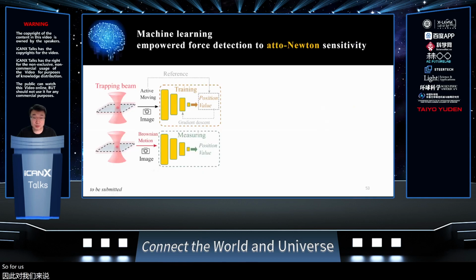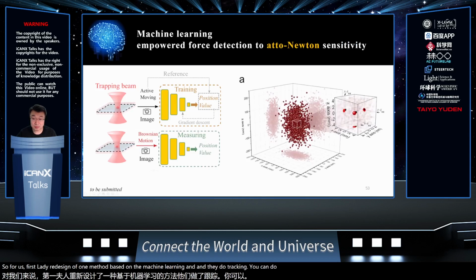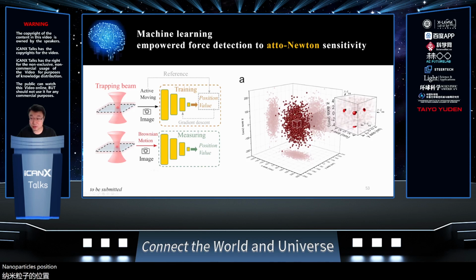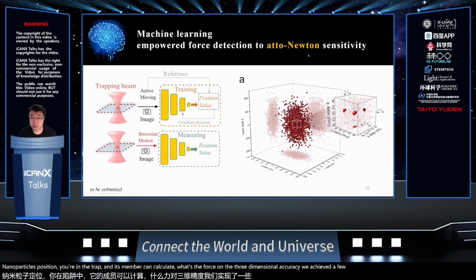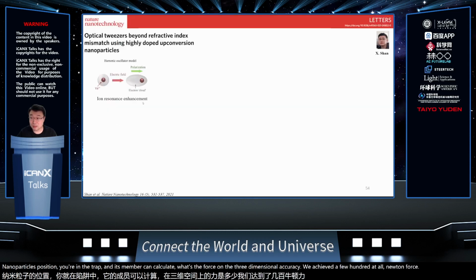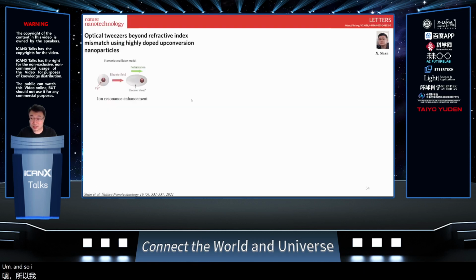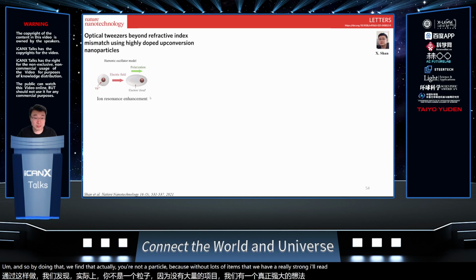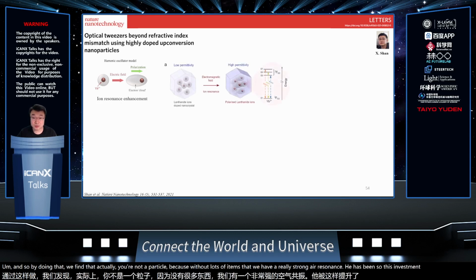So for us, firstly, we designed a method based on machine learning and video tracking. We can make a three-dimensional map of the nanoparticle's position during the trap, and then calculate the force in three dimensions. Actually, we achieved a few hundred attonewton force. By doing that, we found that in our nanoparticle, because we dope lots of ions, we have a really strong ion resonance enhancement. This enhancement is really amazing.